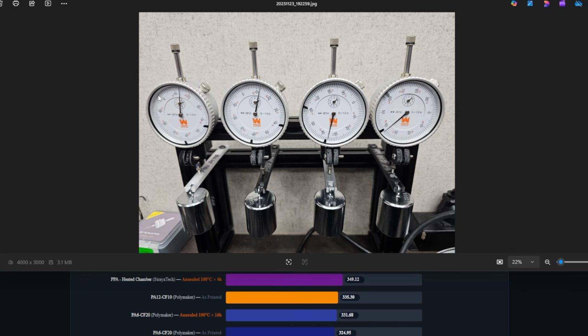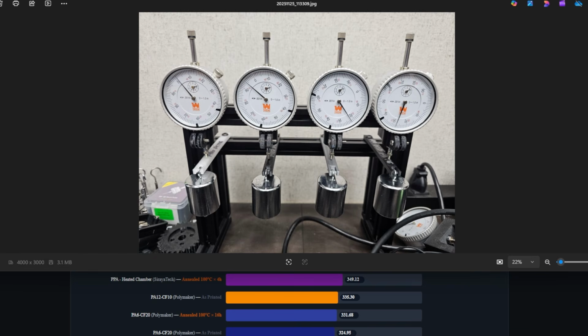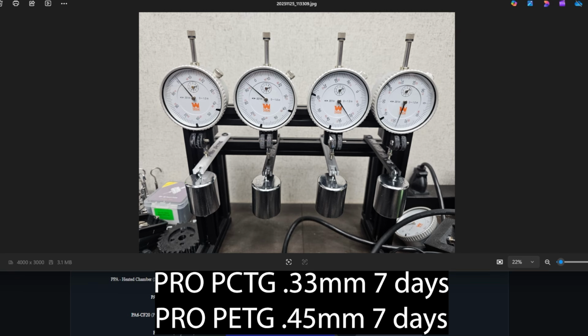So this started at 0 and it's a 0.86 inches. This one is a 0.88 inches. Then we go to the end test here. This is at the very end, and this was showing a 0.99. This is showing a 1.06. So over 7 days, this deflected 0.13 inches on the PCTG and 0.18 inches on the PETG, which is 0.33, 3/10 of a millimeter here, 0.45 millimeters here.